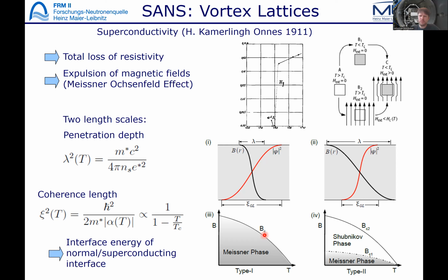For these type 2 superconductors, the phase diagram is shown here on the right-hand side. They split up into two phases. We have the temperature and the field axis here, and we have the Meissner phase where the superconductor expels the magnetic field, and we have the so-called Shubnikov phase where the magnetic field enters the superconductor in the form of superconducting vortices. So the superconductor wants to maximize the interfaces between normal conducting regions and superconducting regions, and therefore the solution was found by Abrikosov.